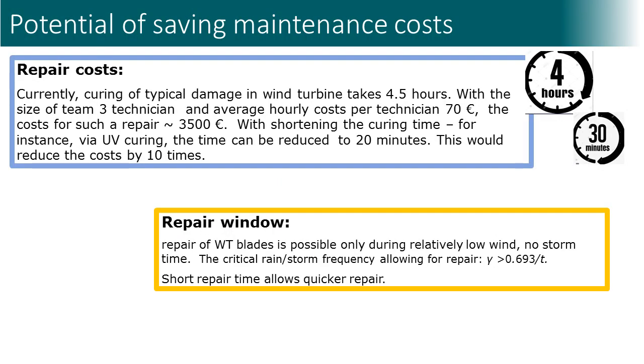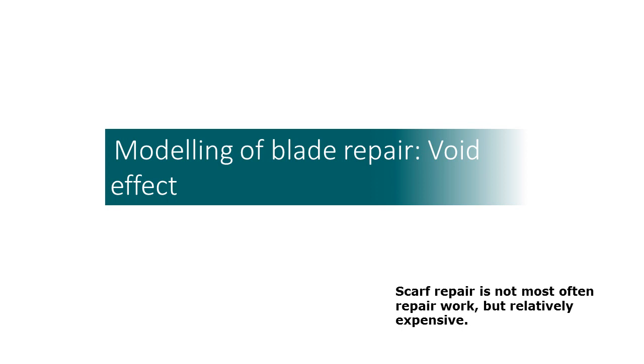Among other things, we can see one possible solution to reduce the repair costs by reducing the curing time. For instance, by using ultraviolet curing, the repair costs can be reduced by up to 10 times. Further, quick repair allows easier choice of repair window. Changing adhesives and their curing conditions should not compromise the repair quality. So, how do the parameters of blade repair influence its quality? To answer this question, we developed a computational model of blade repair.